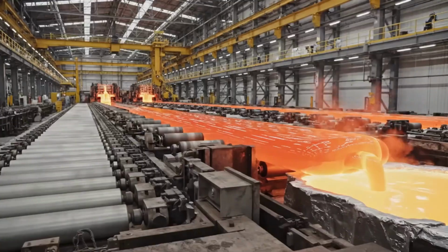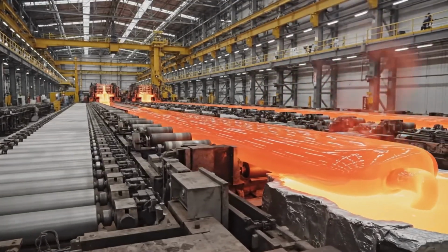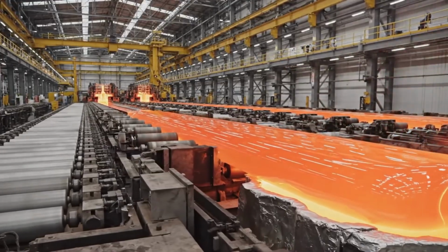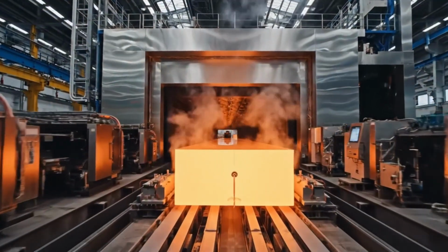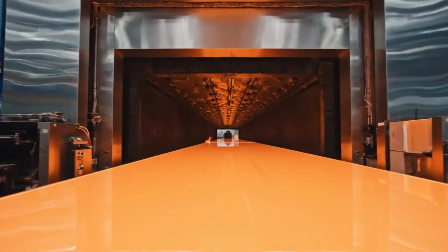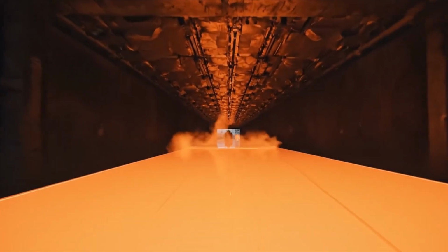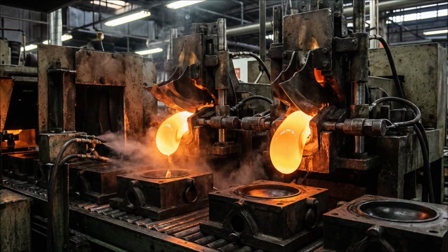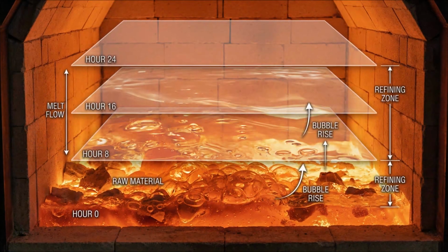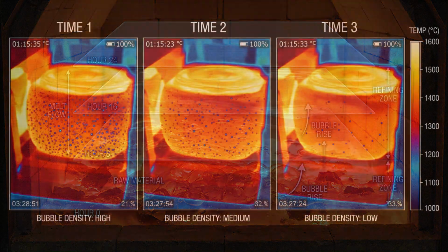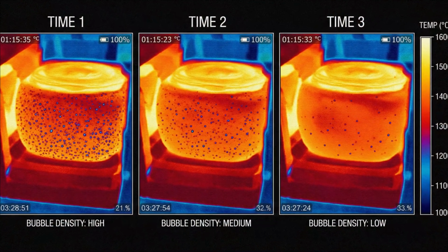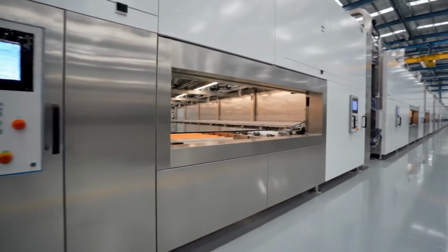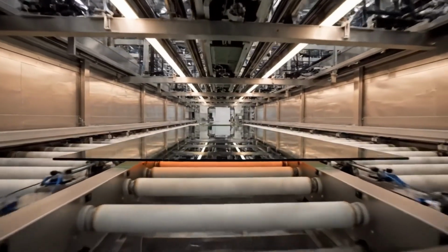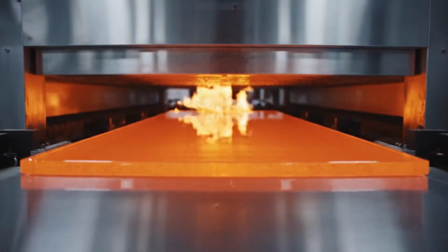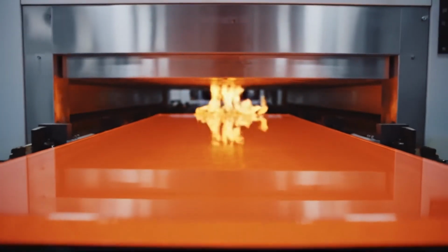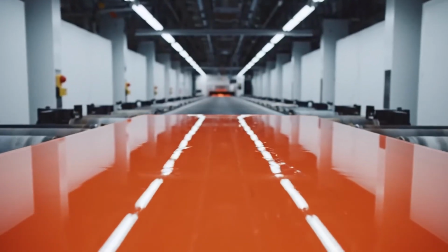The furnace runs continuously for years, but one 8-degree drift nucleates crystalline stones that fracture bottles. This is the part no one sees. The operating temperature is 1,500 degrees Celsius. The tolerance window is plus or minus 8 degrees. Gas flow is adjusted every 2 seconds. Thermal zones are mapped at plus or minus 3 degrees resolution. Regenerative burners recycle exhaust heat. Thermal imaging cameras are embedded in refractory walls. PID feedback loops adjust natural gas flow in real time.